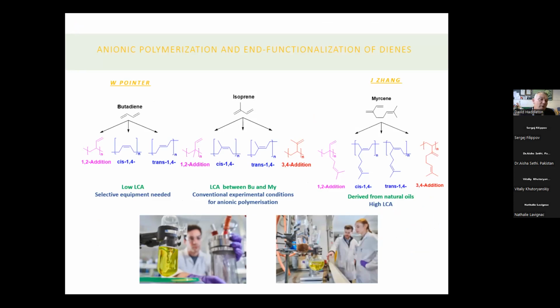One of the things you may or may not remember about anionic polymerization of dienes is that we can control the stereochemistry by just changing the solvent, to be honest. And so we've got myrcene, we'll have these isomers, and isoprene these and butadiene these, really. And what we want to do is control the amount of this 1,2, because these double bonds will do subsequent reactions at different rates. And what we want to do is selectively react the 1,2 and then hydrogenate out the 1,4.